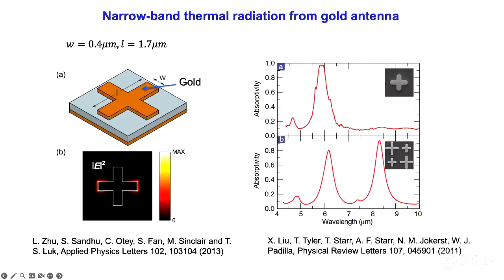And there's also the possibility to create narrow band thermal radiation. In other words, a thermal radiator that doesn't look white, but rather emits only near a single color. And here is a work from Willie Padilla's group. He looked at these gold micro antennas. So this is a cross made of gold with a size on the order of a few microns. And what he sees experimentally is that for these gold antennas, the thermal emission is highly narrow-banded.